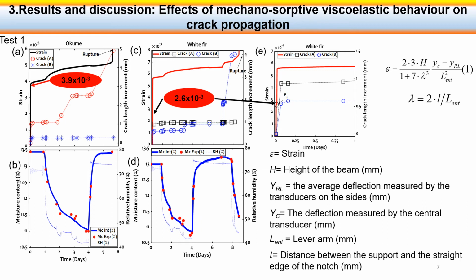After loading, the wood shows a viscoelastic behavior. During this phase, the crack increment remains almost constant. But after the first drying, the wood shows a mechanosorptive behavior, and the crack increment tends to increase until the rupture of the beam. In the white fir test, the rupture occurred during the drying phase, while in the Okume test it occurred during the wetting phase. During the second humidification on day 4, two types of phenomena are observed, mainly pseudo creep and pseudo recovery. These phenomena are explained by moisture expansion.